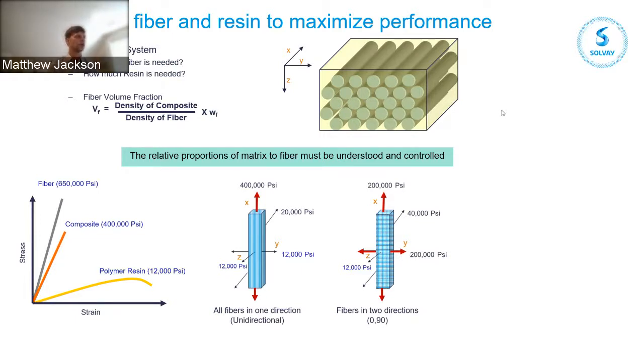And so going from that left-hand image to now the right-hand image, you can see running in the X direction, we've actually dropped our strength and dropped our stiffness by putting plies in the transverse direction. So we've increased the transverse direction, but it's come at the sacrifice of the longitudinal direction, and we've increased our shear a little bit.